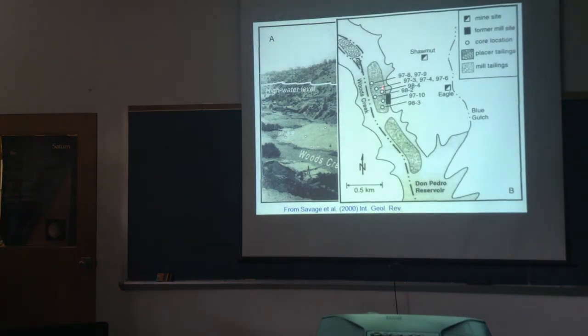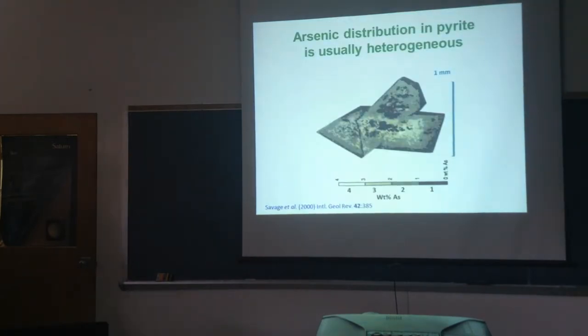And this shows the location of some of the cores that were done in the old historic mine waste just offshore of the Shawmut Eagle mines. This is one of the SEM photos from her work. This is actually a backscatter image that shows the mean atomic number, and you can translate that into higher arsenic when you get to a higher average number, and that makes a brighter color.